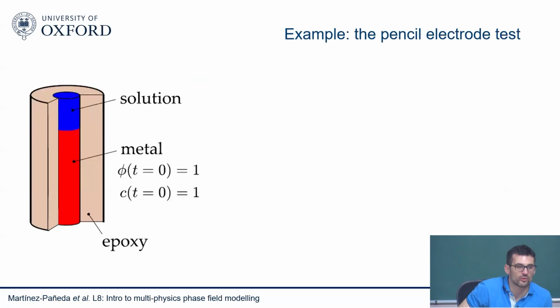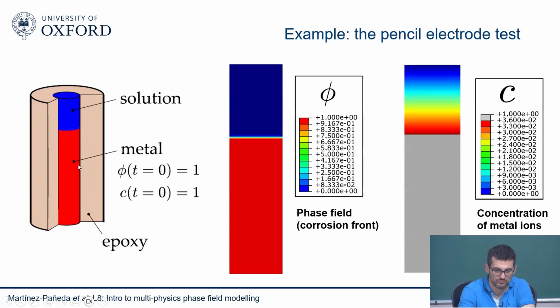So then I'm going to show you a little bit how this model will work, and I'll do that with a very classic benchmark, which is the pencil electrode test. Here you have basically a bar of metal, exposed to a solution and covered by an epoxy. So this is basically a 1D problem. You have 1D corrosion. You have the solution, the metal losing atoms, the metal reducing its size and the solution progressing. So this is what you see basically.